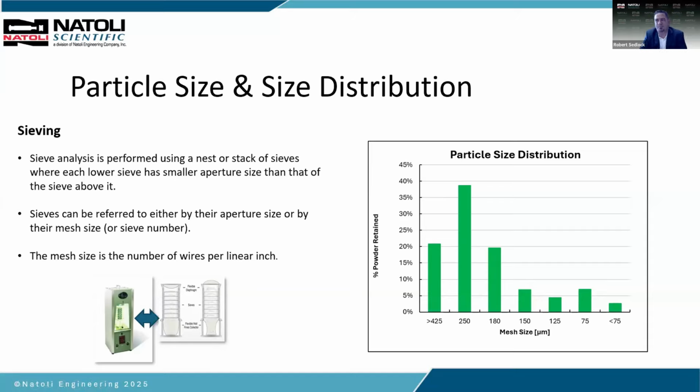Now, USP, United States Pharmacopoeia, defines a fine to be 125 micron to 180, and very fine, less than 125 micrometers. 100 microns is a very nice size for making tablets. Like microcrystalline cellulose, Avicel 102, or Emcocel or ProSolv 90 micron.